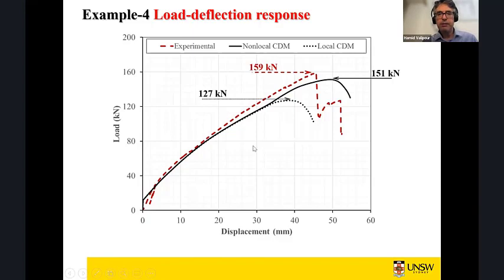Likewise, when we look at the load displacement, you see the peak load from basically the experiments. The dashed red line is 159. If we use that model with non-local model with localization limiter, we get a peak load of 151. If you use a local model, you get 127 kilonewton. And you see there is a difference.